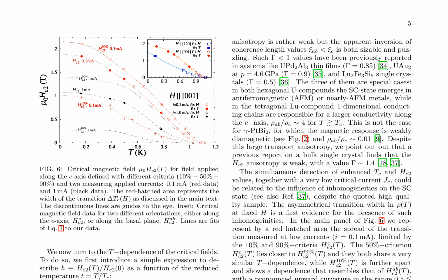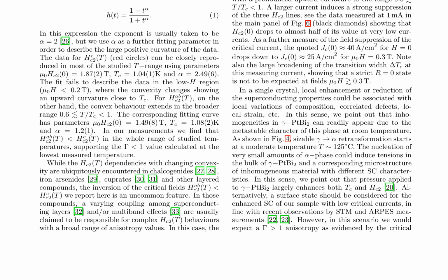In the superconducting state of γ-PtBi2, critical magnetic field dependencies exhibit unique characteristics. The critical field ratio H(T) is expressed as a function of reduced temperature T, with the exponent alpha serving as a fitting parameter to describe the curvature of the data. Notably, the data reveals a large positive curvature, particularly in the low-field region, indicating an upward curvature close to the critical temperature Tc. An uncommon feature of the critical fields is observed, where Hab_c2(T) is less than Hc_c2(T), attributed to the anisotropy in the coherence length values.